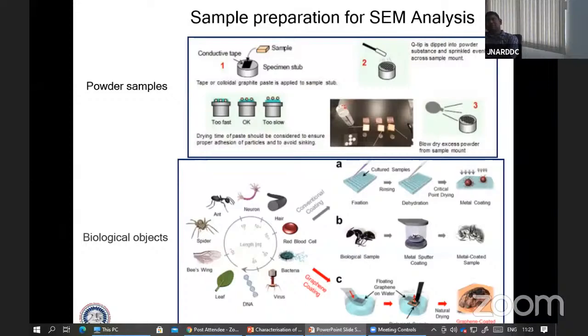The other method is graphene coating, where we prepare some graphene layers, and these graphene layers are floating on water. With an instrument, we fish out the graphene layers and place them upon our biological samples. Then we keep it for drying, and our sample will be ready for SEM analysis.